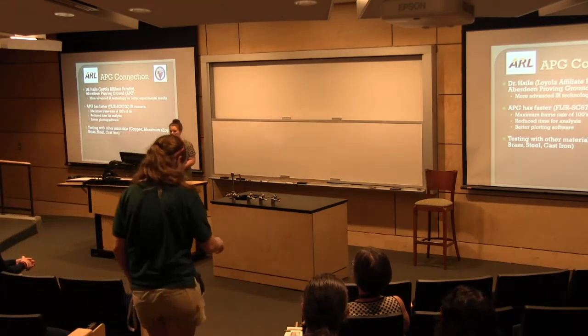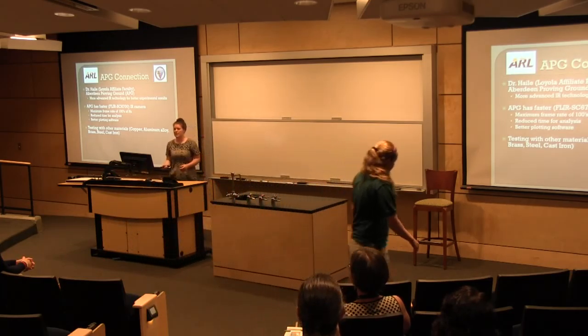So it has a maximum frame rate of hundreds of hertz. So we can actually go up to, I think it's 600 hertz max, which is way better than our cameras. We're actually able to find data more accurately. This also had a better plotting system, so the software we were using was way more advanced. So we were able to look at different types of data analysis for that. And then we went into testing other types of materials. As I said before, primarily all of our data was captured around gray cast iron, because that's experimentally what we had seen. But so we went into copper, aluminum alloy, brass, steel, and cast iron.